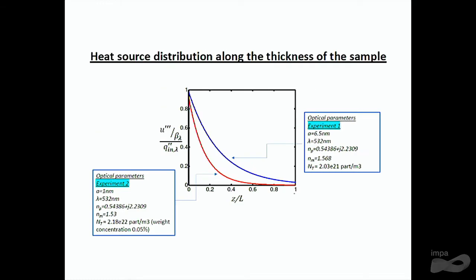Something that is interesting to see is how the heat source distribution for each case is. As you see, this is a normalized plot. The optical parameters in experiment 2, the one that I showed you before, are the following. And the difference with respect to experiment 1 is the size of the nanoparticles. As you see, you have 6.5, the radius in this case, and 1 nanometer in this other case. And also the concentration of nanoparticles is different in each case.